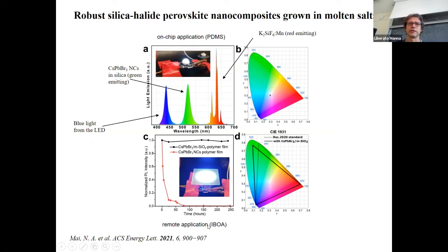Another application we tested, done in collaboration with Quantum Solutions, is again a blend of two emitters. So our composite and the standard red emitter, together also with titanium dioxide as a scatterer, in a curable polymer, IBOA. And also we got white light emission.